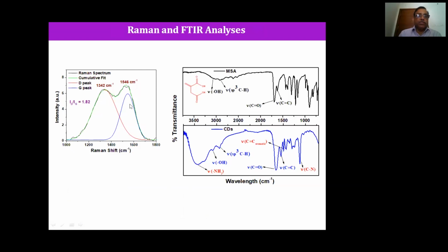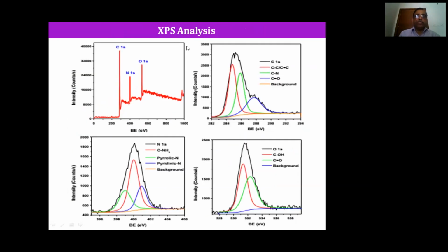Raman analysis gives information about the ratio, which is 1.8. The IR analysis gives information on the functionalization of this material. XPS gives information on the composition - carbon, nitrogen, oxygen - which helps us identify the composition of the material.